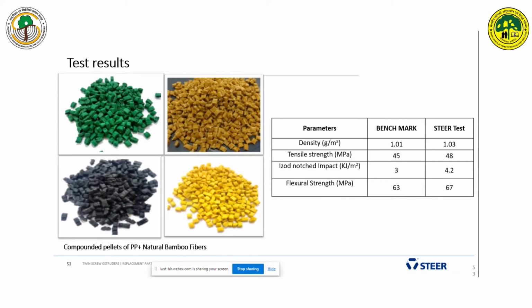And the benchmark we got from the customer was 45 tensile strength, and the STEER test results are higher using FGT technology. Also a slight improvement in the impact strength and flexural modulus.